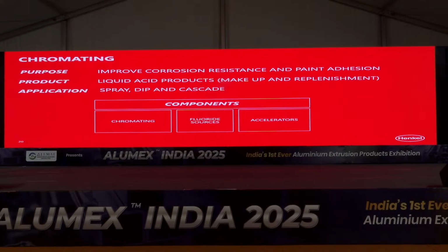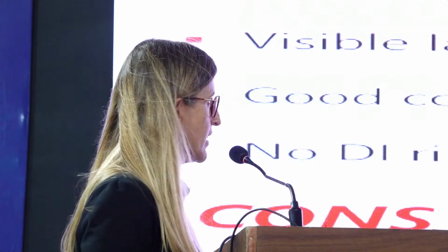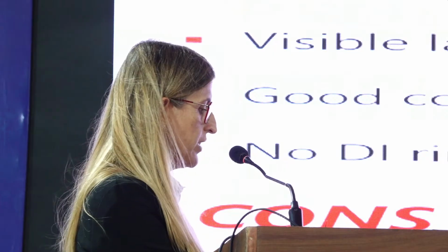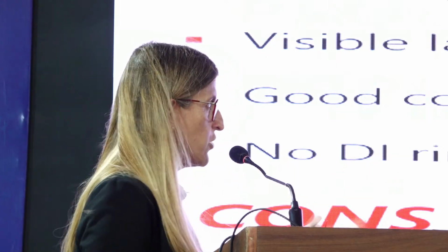In the conversion, we have different types. It is true that in the last years the typical process was a chrome 6 process, which improved the corrosion resistance and the paint adhesion. These products are liquid products, you can use them in all the pretreatments, and they are based on chromate, fluorides, and accelerator. But as Henkel, and because sustainability is our main concern, we have alternatives to chrome 6. It is true that chromating is quite reliable and has color, so it is really easy to differentiate whether the material is treated or not, because you can see color on the surface.